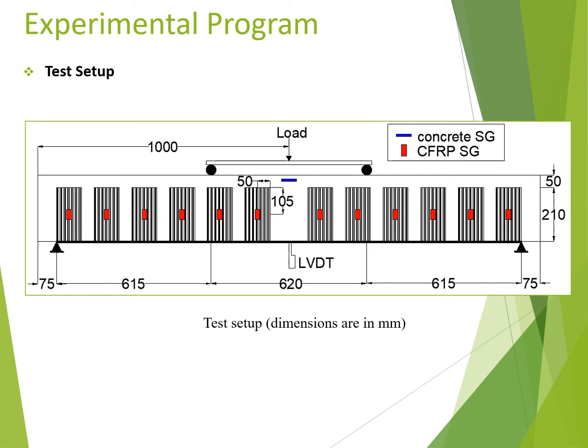In addition, strain gauges were placed onto the center of the U-wraps on both sides of the beam to monitor the strain in the CFRP U-wraps. One strain gauge was mounted onto the concrete to monitor the strain in the concrete. One LVDT was placed mid-span at the bottom of the beam to measure the deflection of the beam.